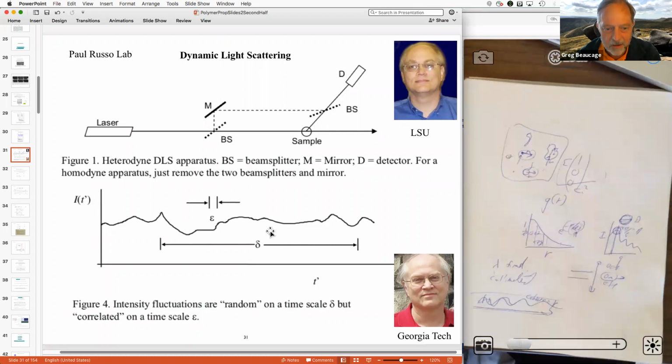So it's flickering. And that flickering has to do with how fast the bead is moving through, and how fast it's moving through has to do with the diffusion coefficient, right? It's being driven by kT, and it's being slowed down by the viscosity. And the ratio of the kT to the viscosity gives you kind of a time, right? A speed. So basically, the rate of flickering is going to tell you the diffusion coefficient of this thing.